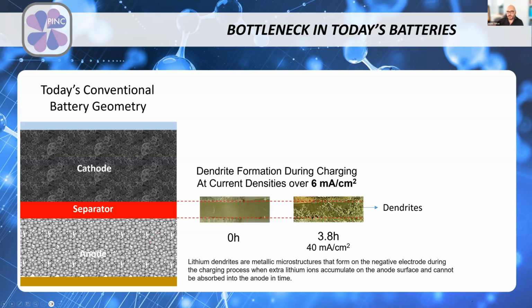Right now that is the main limitation. That's the reason why we cannot charge really fast. At some point the ion current density increases so much that the dendritic formation becomes out of control. Once you short it, you basically break the battery. We try to keep the ion current density down by slowing down the charge and controlling the porosity, the electrolyte formulations, and the ionic conductivity in the separator.